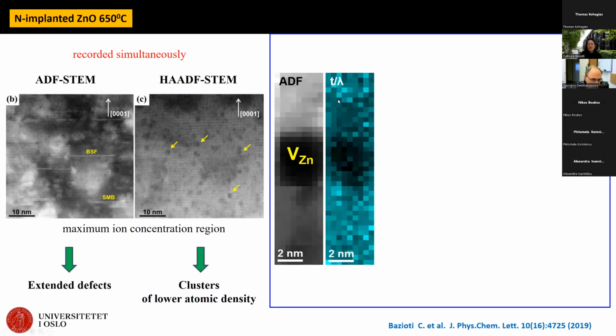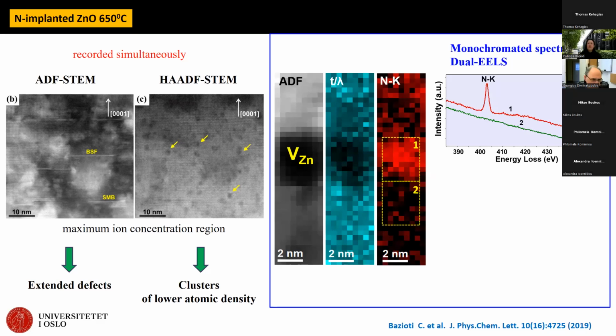corresponding relative thickness map acquired by low-loss EELS. We can see that we have a drop in the intensity. So this is an indication of a depleted area, a zinc vacancy cluster. You can see the size, it is only 2 nanometers in diameter. And then by extracting the 2D maps with core-loss EELS, this is the nitrogen K peak, you can see that we had nitrogen signal only inside these zinc vacancy clusters. And then it abruptly disappeared outside this cluster. So we have localization of nitrogen exactly in this zinc vacancy cluster.